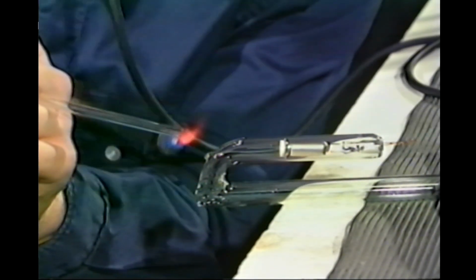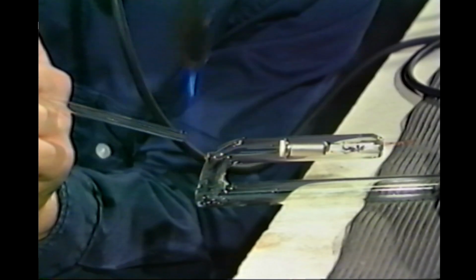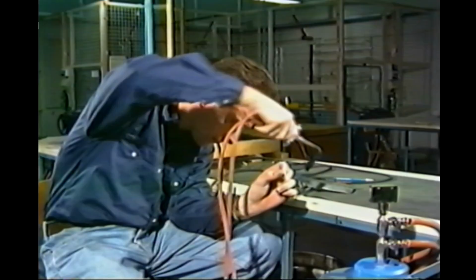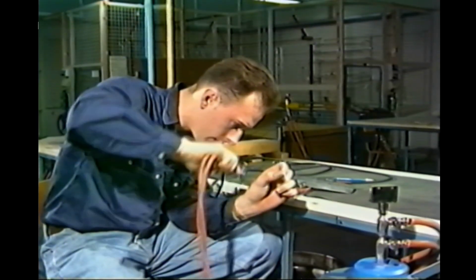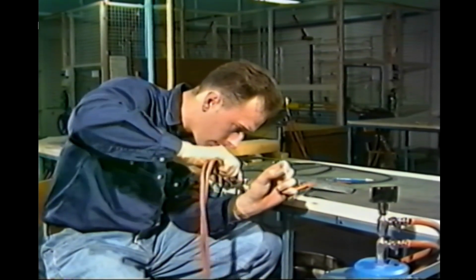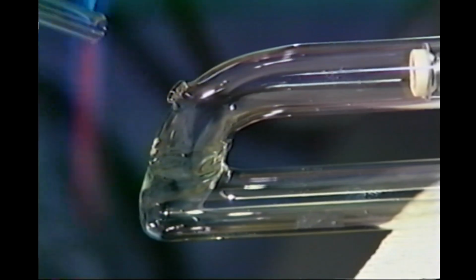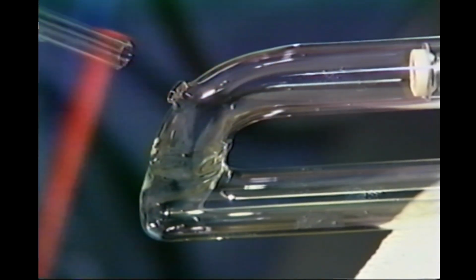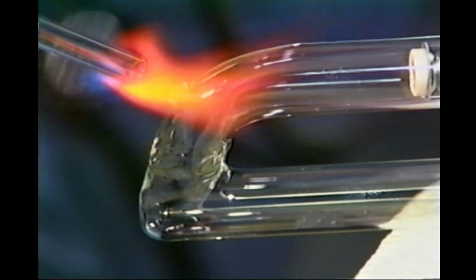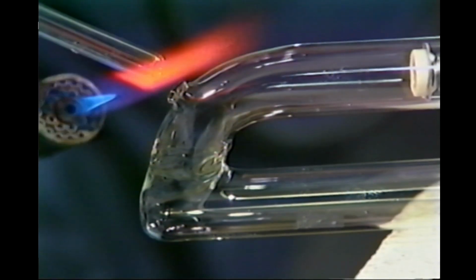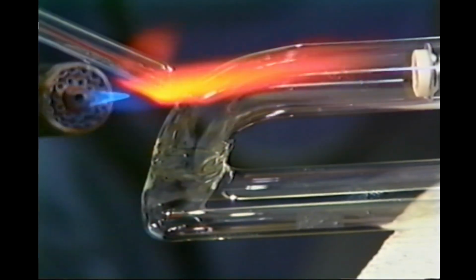Using the same small sharp flame, begin by melting the open end of the pump stem. The stem is usually a 15 cm length of 6 mm diameter tubing. Bring the pump stem into line with the hole and, keeping the flame at right angles to the pump stem, melt both parts using a full rotation of the flame.